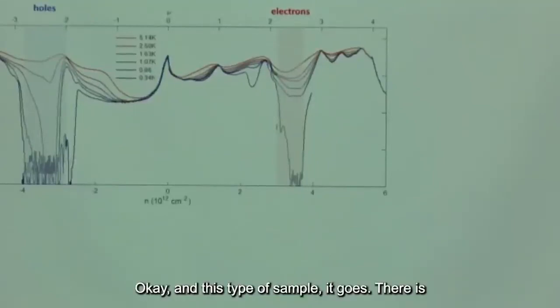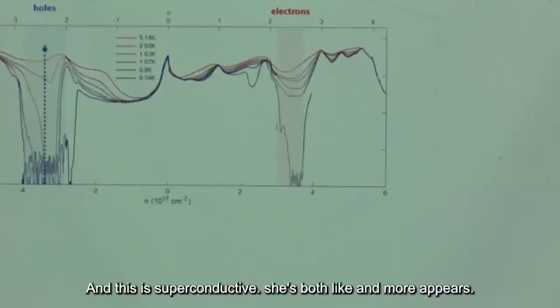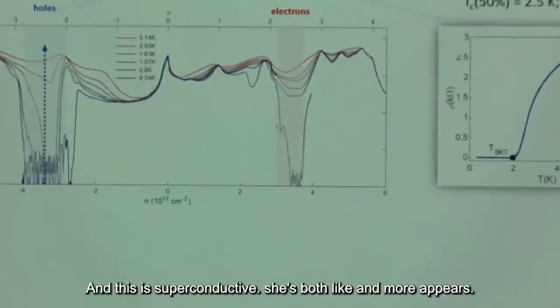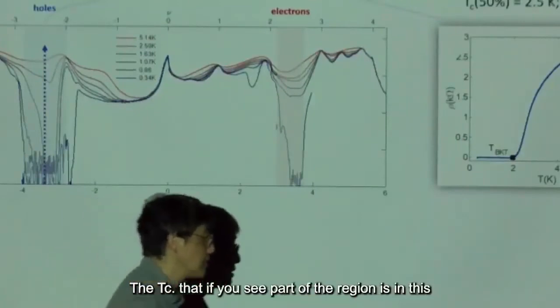So near the flat band, you see that superconductivity appears, on both the electron and hole sides, and it has a little bit higher TC than TBG. Part of the reason is the renormalization of the multiple layers; at least at the magic angle, we have a little bit larger coupling than the twisted bilayer. And that will provide higher TCs in the system.